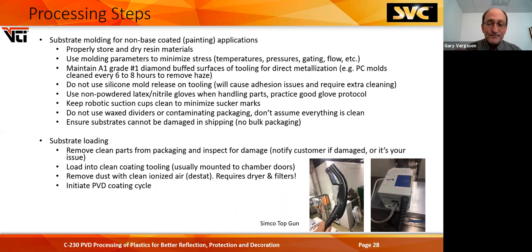Why are we worried about stress? If there's a lot of stress or stress areas in the part, the PVD coating doesn't stick as well. You need to maintain a grade one, A1 grade, number one diamond polished surface on the tool for direct metallization. And in polycarbonate, you're going to be cleaning those molds every 6 to 8 hours to take off the haze that builds up on the part, because that haze will transfer itself into your parts. You can't use mold release on your tooling, and you know it can be done. They do make special grade metallization resins that will come out of the mold, but if you're a shop that sprays mold release on the tool, you're going to have nothing but problems.